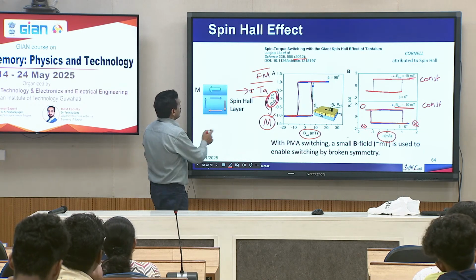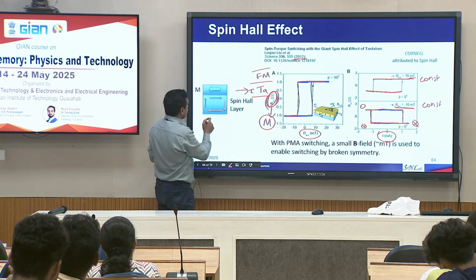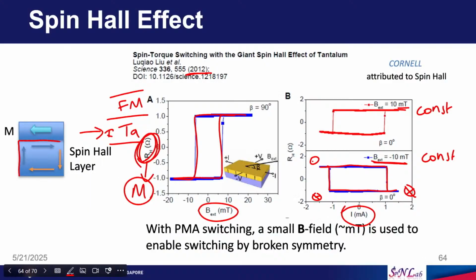Okay. So, what happens is when they send current, let us say now this is a cross sectional view. This is a tantalum for example. When you send the current through the tantalum layer, one type of spin accumulates here, another type of spin goes into the opposite direction, then you can see down spin is here, up spin is here. So, they typically follow this circular relation. So, spins go to the different edges of the heavy metal layer. So, when this type of spin goes up, it can switch the magnetization from pointing left to right.